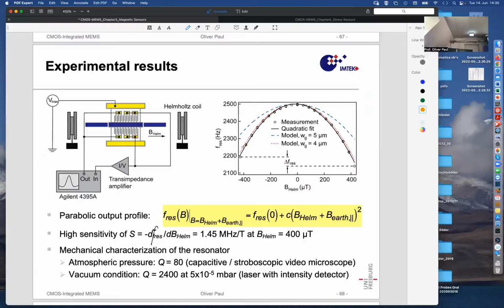You notice that we can measure much smaller fields. It's interesting to know that you can measure fields by having a delta F, so this would be some resonance frequency change, delta F resonance frequency. Really the main thing is that it's quadratic, so it's totally unhandy for small fields, and it's direction insensitive. But thanks to the magnetic field of the Earth, we saw that there is a split. And if the Earth's magnetic field was pointing in the other direction, we would have the split in the other direction.